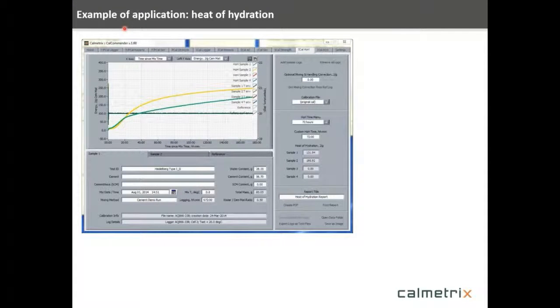All right, now let's turn our attention to applications that are mostly related to the isothermal devices, where we can quantify the data. So one is heat of hydration. Heat of hydration is a term in the cement and concrete industry used to basically measure the amount of heat that gets generated from the reaction, which is basically an integration of the power curve. So we're looking at joules per gram of material at a particular time.